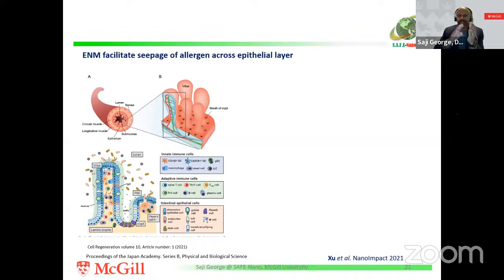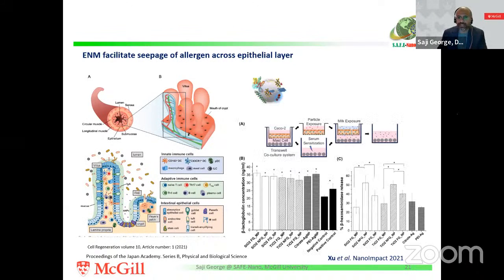Now, when these tight junctions are compromised, we saw, as we did in some of the experiments with a co-culture model, a transwell assay, where we have an epithelial layer on the top and mast cells on the bottom, and we challenge that epithelial layer with the nanoparticles, that the availability of lactoglobulin, for example, has increased in comparison to negative control. There is a substantial, significant increase in the bioavailability of those proteins in the basal compartment, which means they percolated or passed through those epithelial layers.